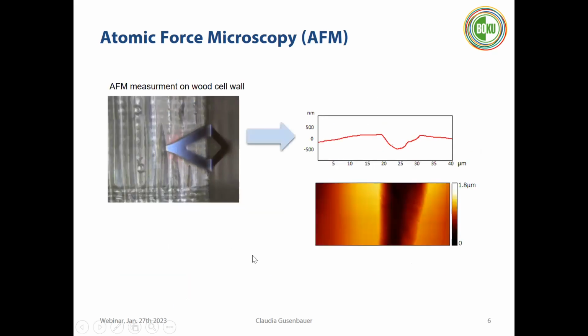So here you can see how an AFM image is generated on a wood cell wall. So we have our prepared wood sample. We scan the wood surface with our tip. The tip is carried by a cantilever. You see it here, like the triangle, moving to the left, to the right in the left image. And the cantilever carries the tip on the bottom side. And you can also see on the left image the laser system, which follows the movement of the tip and precisely captures the movement of the cantilever that carries the tip.